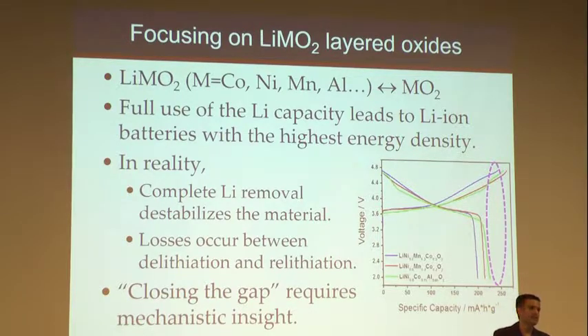M can be almost anything. Right now, the most popular combinations have nickel, cobalt, manganese, aluminum maybe. And so these are the phases that constitute the most focus for application. And so theoretically, you could do the reaction in the top. You could remove one lithium and go to MO2. That would give you 280 milliampere hour per gram. That's right at that top right corner of that map that I showed you.